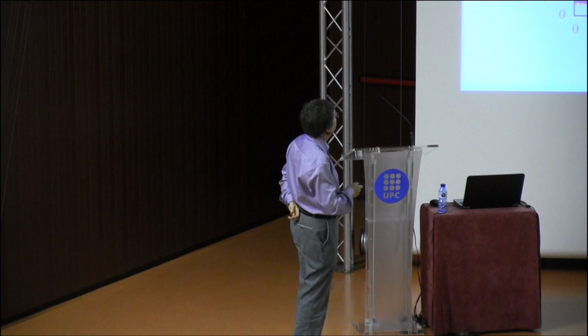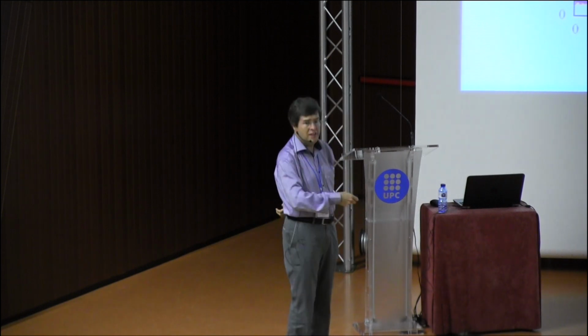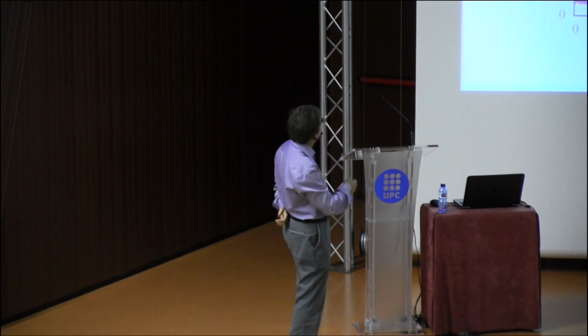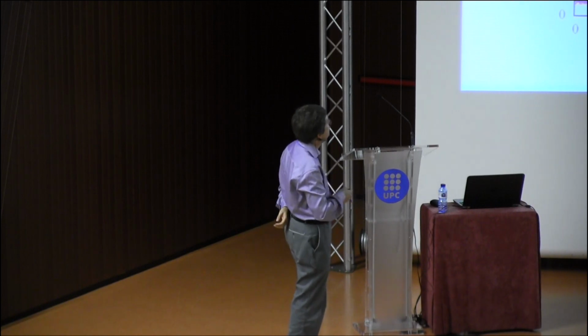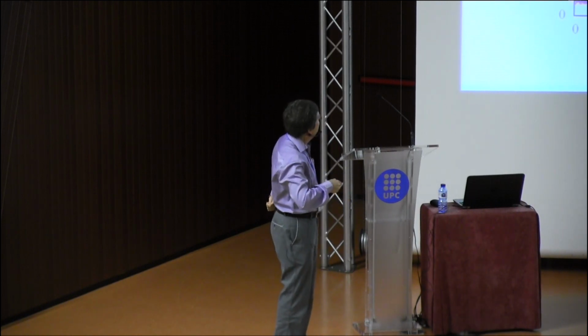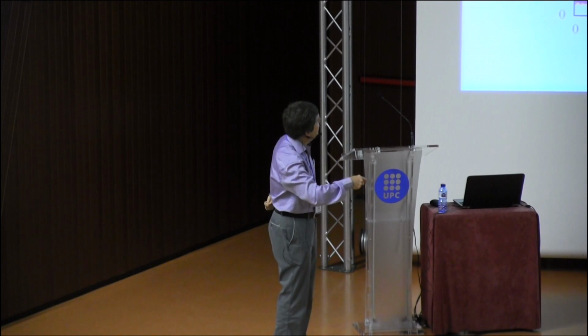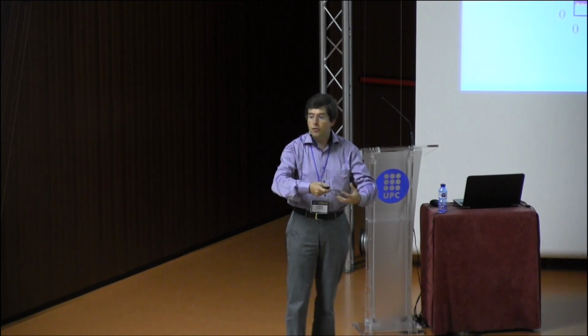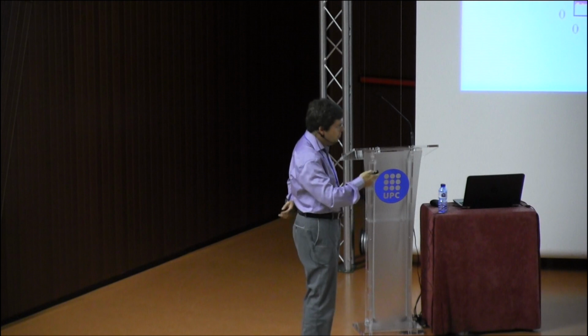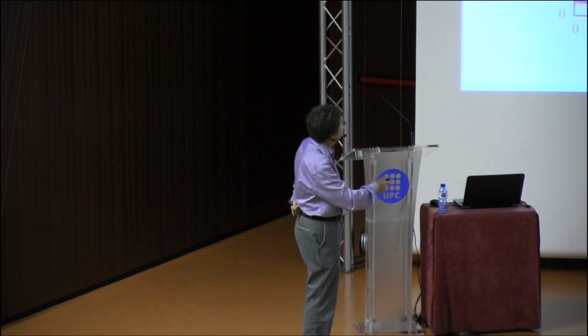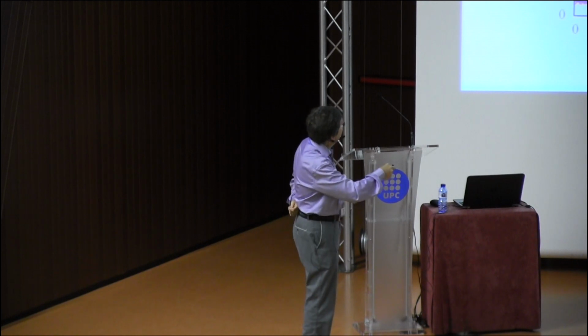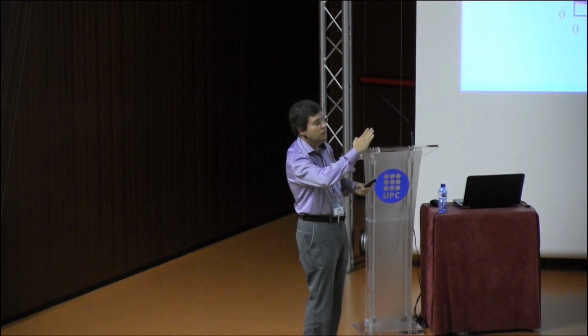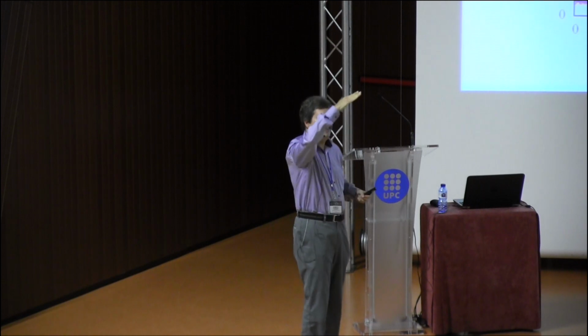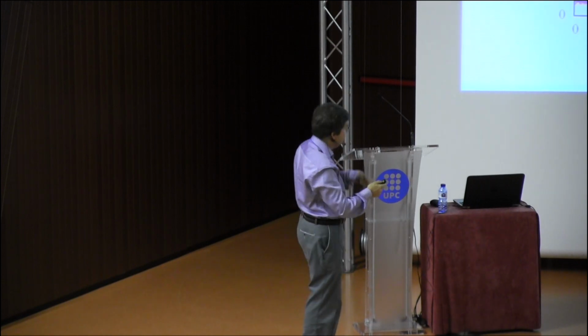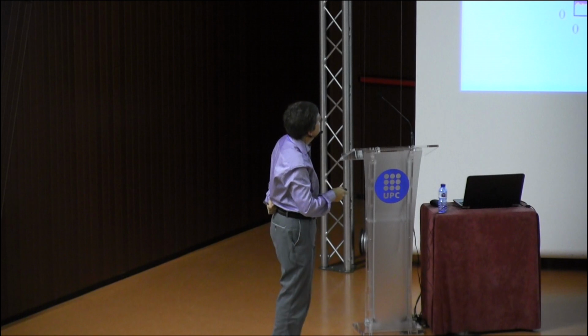If you plot along the axis of the sample the plastic strain or total strain that you measure, at the very beginning you have a bump, which is the localization of the band, and then the band propagates. There are two fronts here, and the irregularities are due to the fact that the band is not nice and straight but rotates a bit, making the field more complicated than in a plain sample.